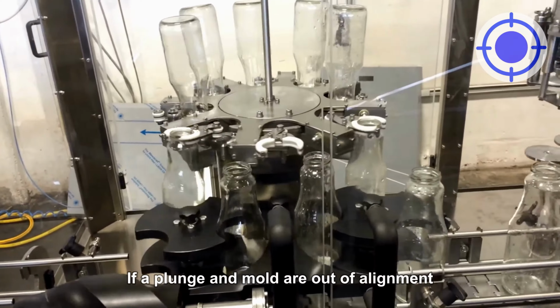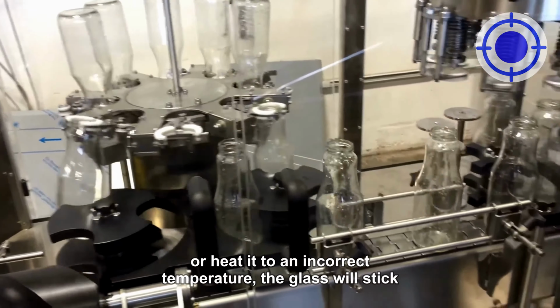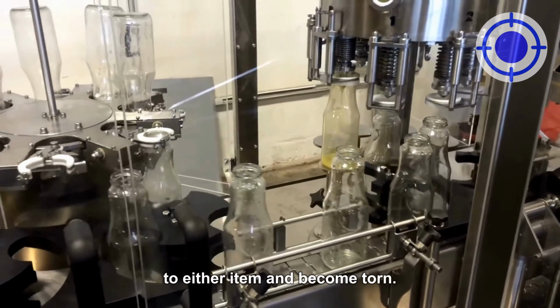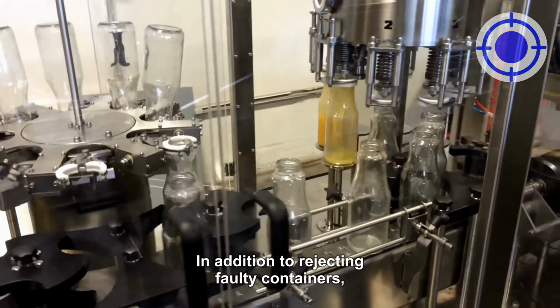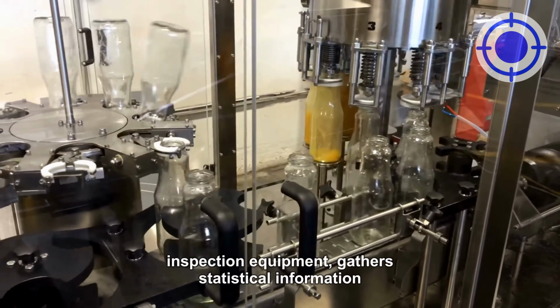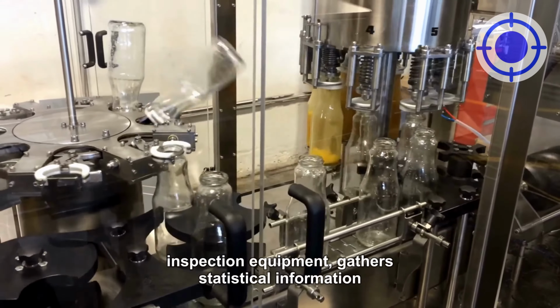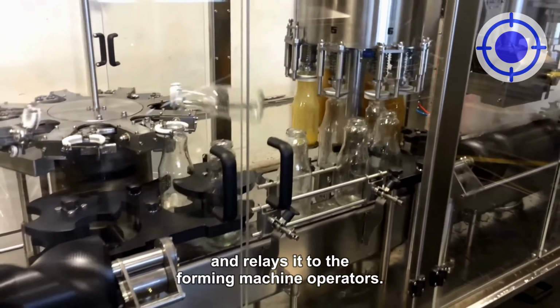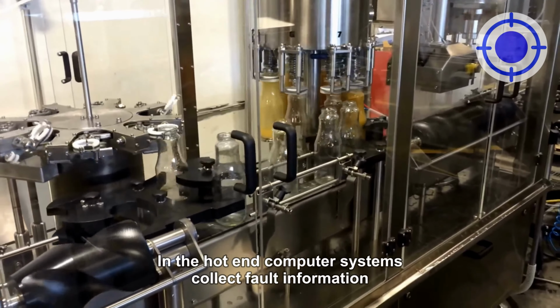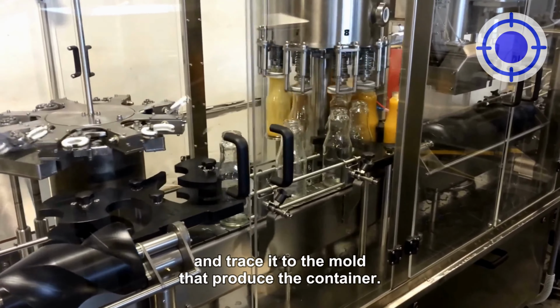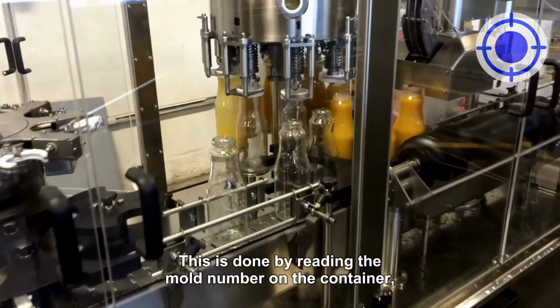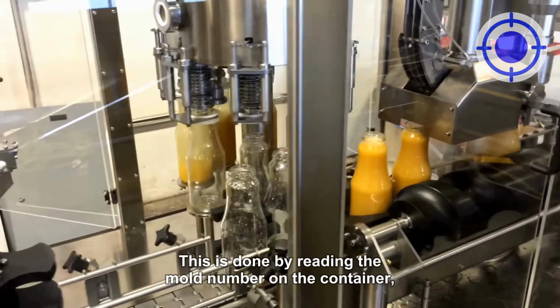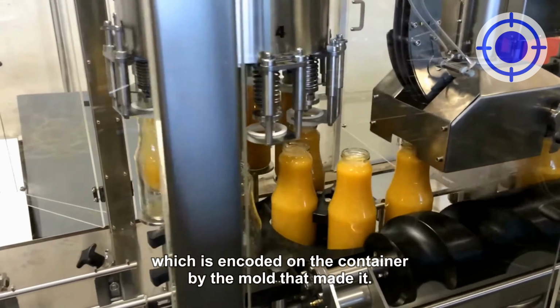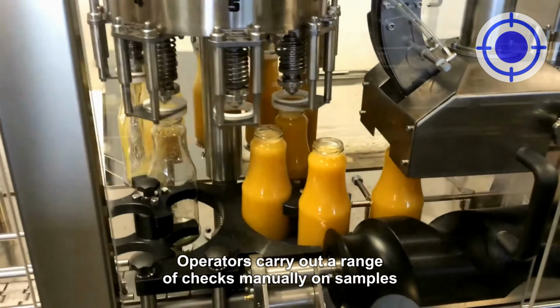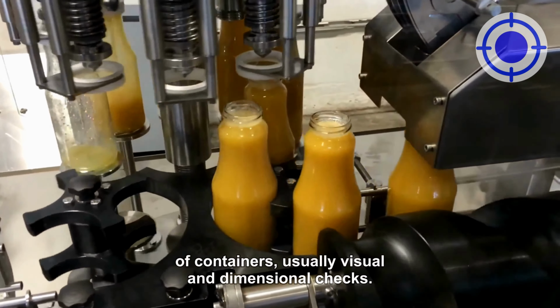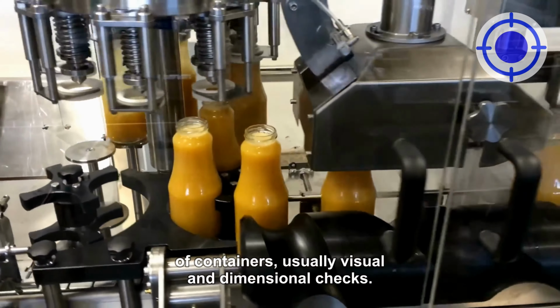If a plunger and mold are out of alignment or heated to an incorrect temperature, the glass will stick to either item and become torn. In addition to rejecting faulty containers, inspection equipment gathers statistical information and relays it to the forming machine operators in the hot end. Computer systems collect fault information and trace it to the mold that produced the container. This is done by reading the mold number on the container, which is encoded on the container by the mold that made it. Operators carry out a range of checks manually on samples of containers, usually visual and dimensional checks.